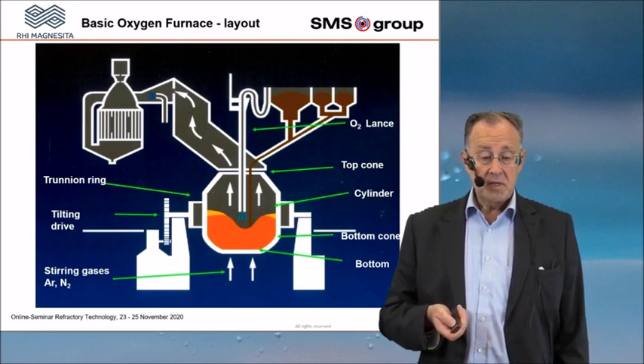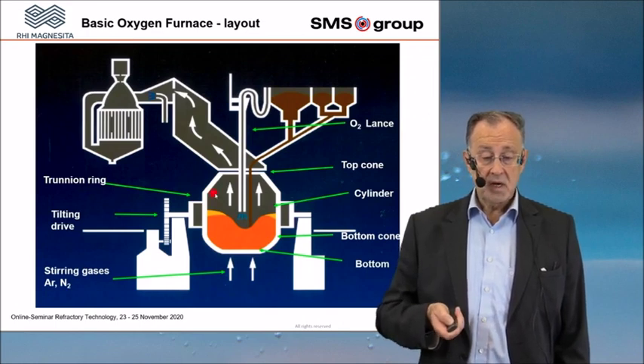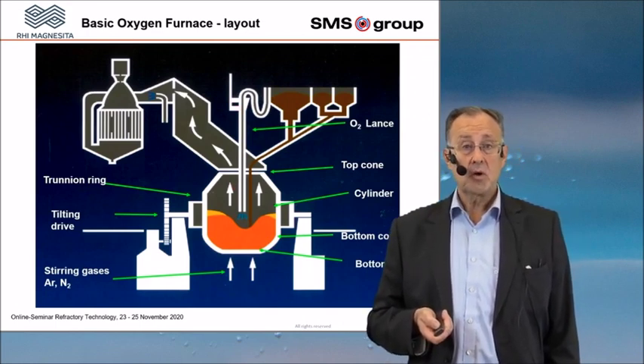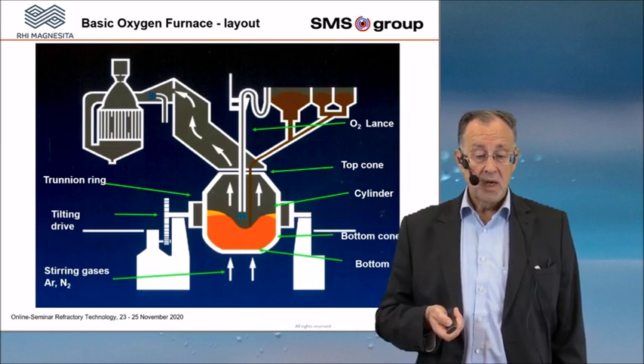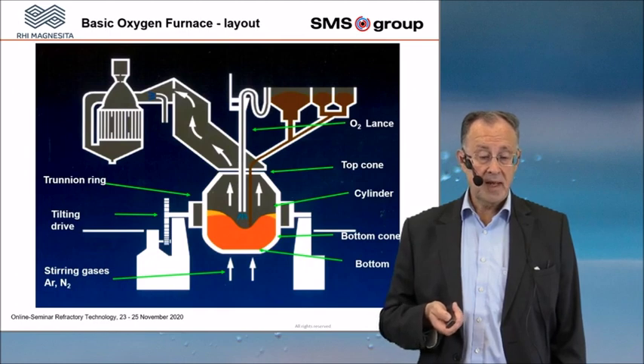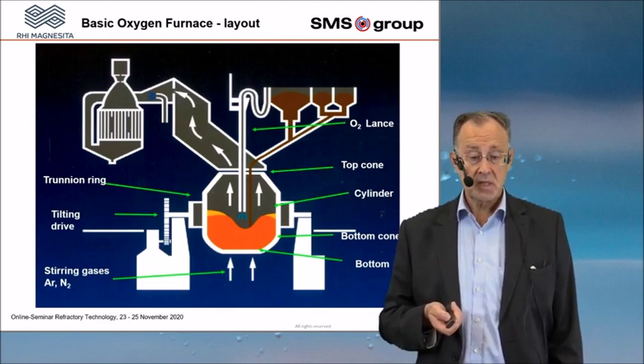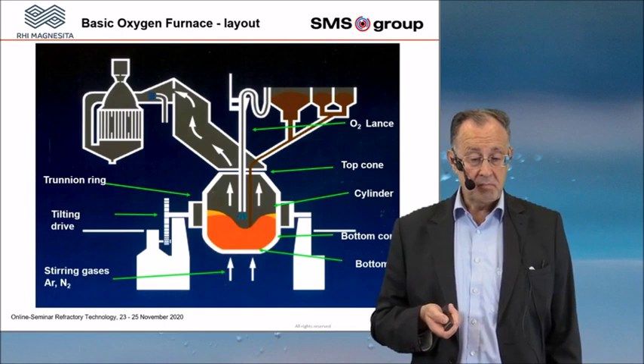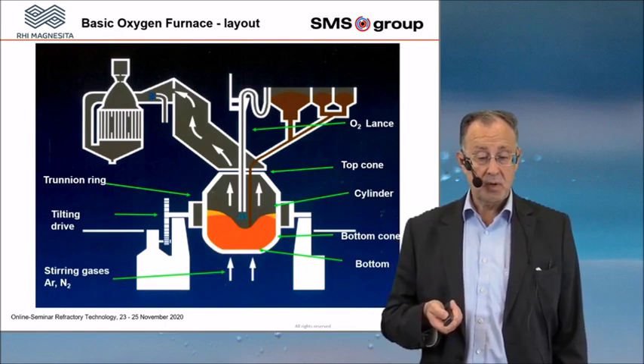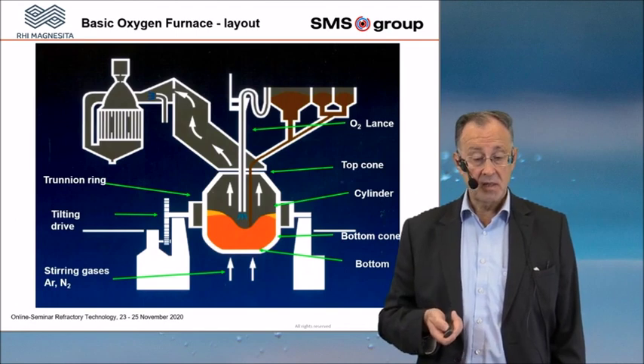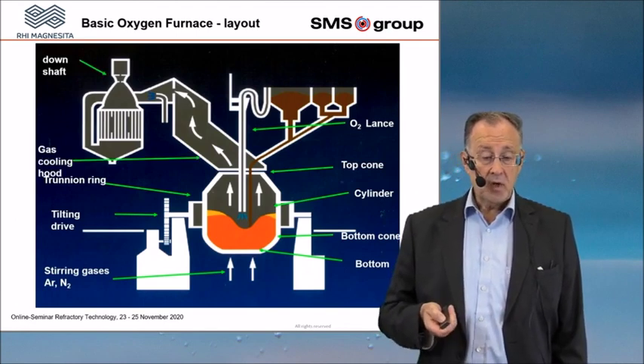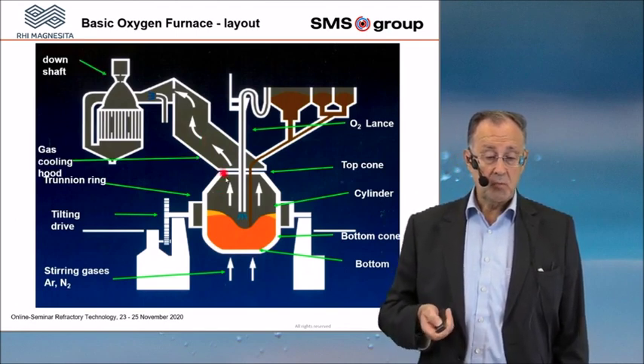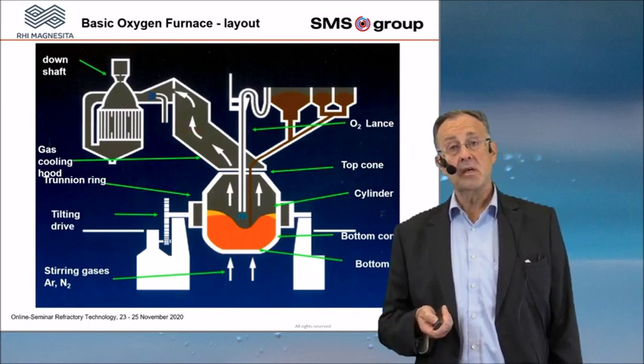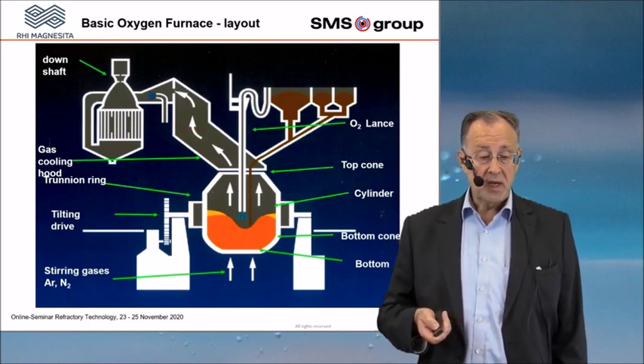Then the big important point here is the oxygen lance. That means you drive the oxygen lance inside the converter, and then you blow the pure oxygen with a certain distance from the lance tip to the surface of the metal bath, and you try to penetrate one part of the oxygen inside the melt. To collect all the fumes and gases coming out of the converter, and this is mainly CO and CO2, you have a gas cooler above the converter.